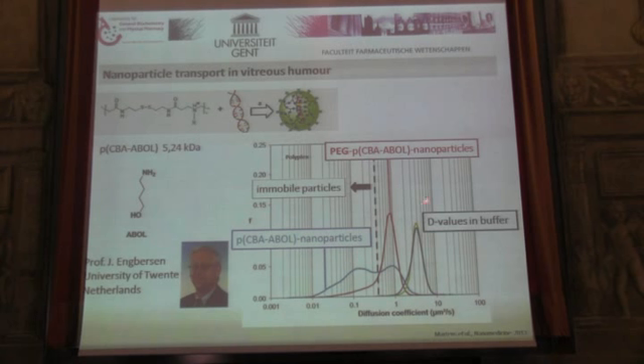And again, we see that, so this is mobility in water. If you inject them into the vitreous, the cationic particles, it's the blue line. Again, this bimodal behavior, it's similar to the artificial particles. And then if we use a pegylated variant, indeed, relative to the blue curve, you see that the mobility again increases. So this is very nice. But as we all know, pegylation is nice for mobility and stability, but it inhibits cell uptake because you also prevent attachment to the cells. And this is where hyaluronic acid might be a better alternative, indeed.